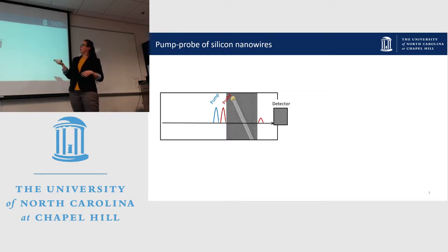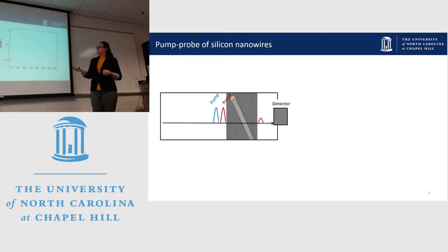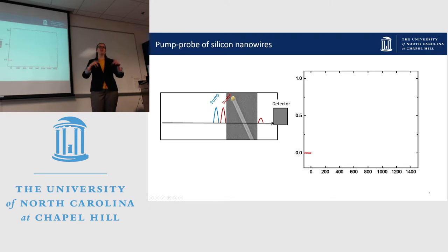So if the probe arrives before the pump, there aren't any photoexcited carriers in the silicon. A lot of the probe light is going to be absorbed, and very little will get to your detector. Here we can plot the signal that we see at our detector against the amount of time between when the probe and the pump arrive. I'm going to define the probe arriving before the pump as being negative time, and if it arrives after, it's positive time. If they arrive simultaneously, the pump excites a bunch of electrons and holes, the nanowire becomes transparent, and we get a lot of probe light at our detector.